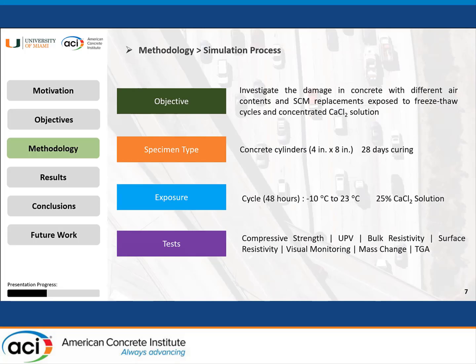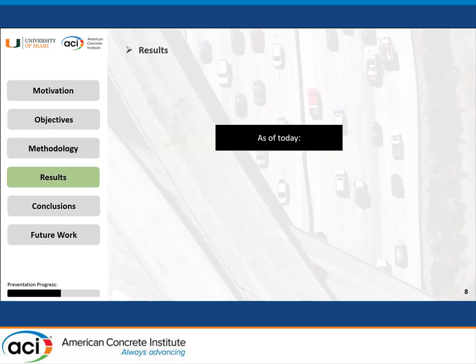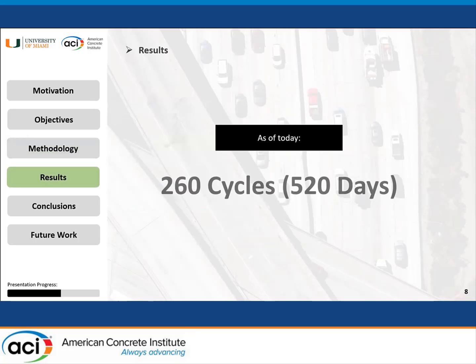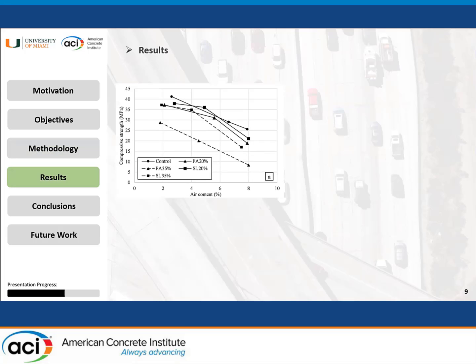And the tests that we utilized for keeping track of these measurements and the damage that was going to happen in them were compressive strength, UPV, bulk resistivity, surface resistivity, the visual monitoring system that we talked about in the previous slide, mass change, and thermogravimetric analysis. As of today that I'm presenting this to you guys, we've experienced 260 freeze-thaw cycles, which is equal to 520 days of exposure. And here I'm going to get to the results so we can spend more time on discussing the results.